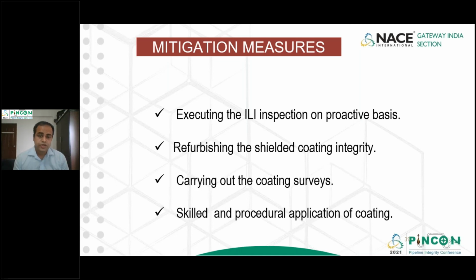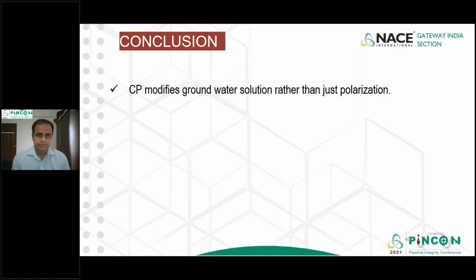Further, the coating surveys, when they are executed by the site technicians in the field, see, an on-the-line survey across the ground layer does not give you a correct indication of your coating health. But carrying out the coating surveys at least eliminates to a bigger extent having failure. Finally, none of the coating products are bad. It is all about the skilled and procedural application of the coating in the field that helps you gain the advantage. Concluding my presentation,